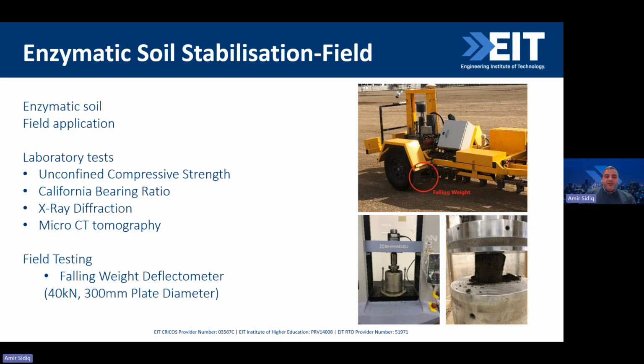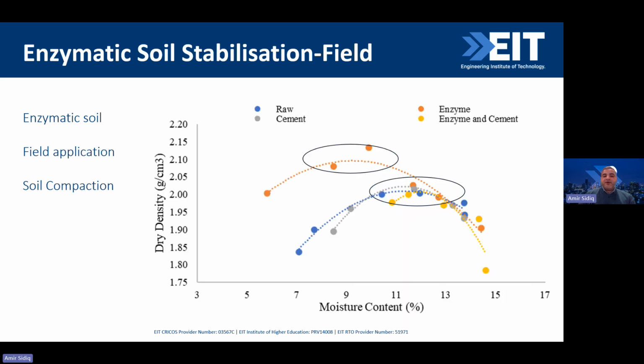The tests we took are the unconfined compressive strength, which is a general test to understand the strength of the soil, the California bearing ratio, known as CBR, the X-ray diffraction, micro-CT tomography, and then we also did field testing, which is the falling weight deflectometer. This is a very precise test from the field, and it's quite expensive in general, but it provides very good deflection data throughout the entire site at very high levels.